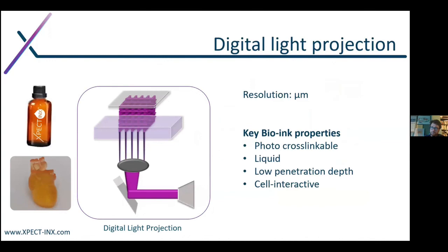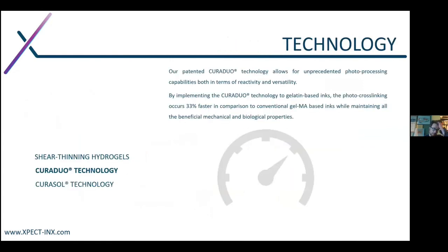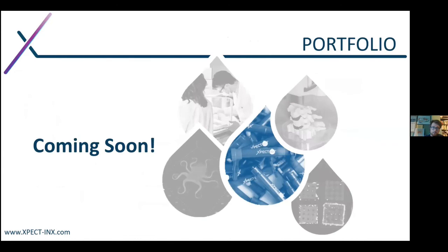So this is single photon processing where you cure one layer after the other. So key bioink properties there. So this is the intermediate resolution in tens of micrometers. So you need to have material which is photocross-linkable liquid, but also you want to have a low penetration depth, so the light doesn't go too deep that you compromise your previous layers when curing the next ones, and you want your material to be cell interactive. Again, here we can take advantage of our Cura Duo technology, and we are currently working very hard in optimizing these formulations, which we hope to present to you soon, still in 2021.